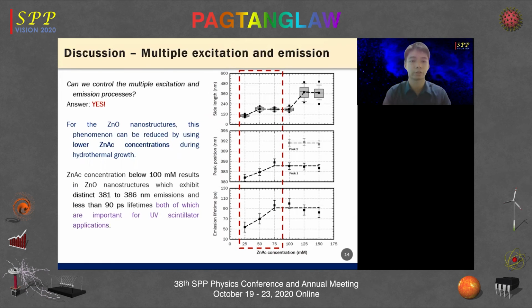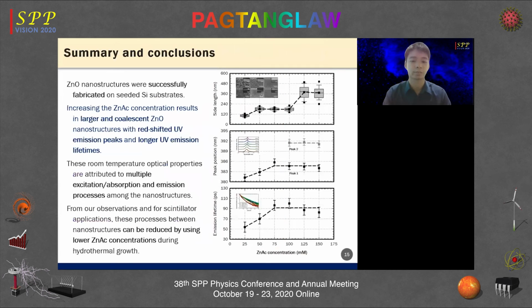concentrations during hydrothermal growth. As shown in the figure, zinc acetate concentrations below 100 millimolar result in zinc oxide nanostructures which exhibit distinct 381 to 386 nanometer emissions and less than 90 picosecond lifetimes, both of which are important for UV scintillator applications. In summary, these zinc oxide nanostructures were successfully fabricated on seeded silicon substrates using different zinc acetate